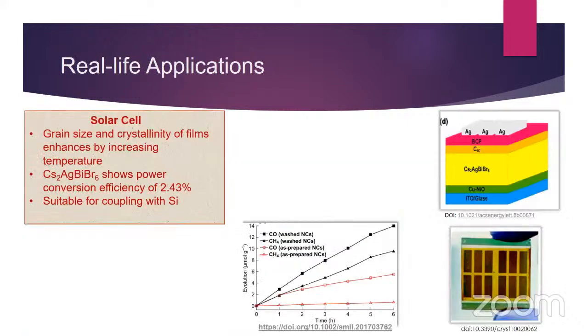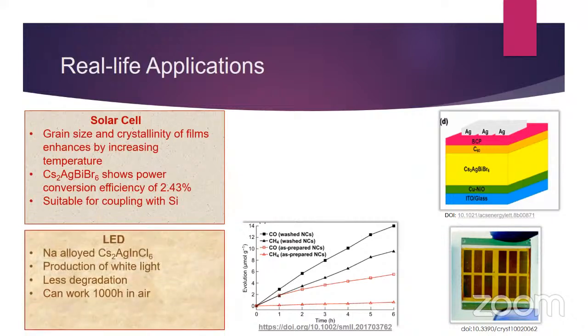The first one is the solar cell. The Cs2AgBiBr6 double halide perovskite shows a power conversion efficiency of 2.43%. Since their band gap is almost similar to silicon, these materials can be suitable for coupling with silicon. The second one is the LED. The sodium doped Cs2AgInCl6 double halide perovskites can be used to produce white LEDs, and they are very stable and can work up to 1000 hours.